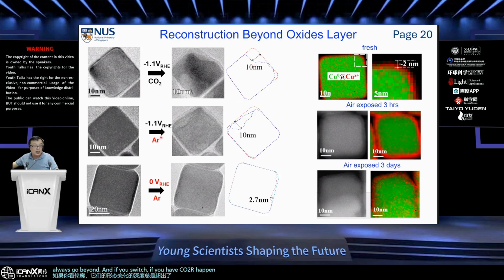If you get rid of the CO2, at this condition there's no CO2R because there's no CO2, only HER, you also behave similarly. And only if you get rid of this negative potential, even at 0 volt, this potential is still enough to reduce the surface oxide. So you will see a much smaller morphology change, and this thickness is usually within the thickness of the oxide. So this tells us there was something else happening, other than the oxide reduction, causing this change.